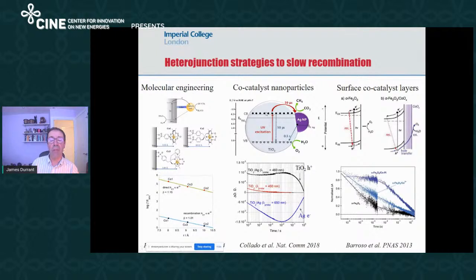This is an example of a particle where simply by putting a silver nanoparticle on the surface of titania, you change the lifetimes of generated carriers. This is for just titania by itself. Almost all the carriers have disappeared by a few microseconds. When you put silver on the surface, the holes in titania live for almost a second. This is because the holes live for a second down here, and the electrons go to the silver nanoparticle. You get a spatial separation of charge, which gains the lifetime, which allows you to turn on, in this case, the oxidation of water and the reduction of CO2 to methane.